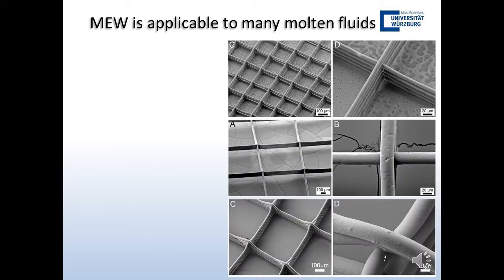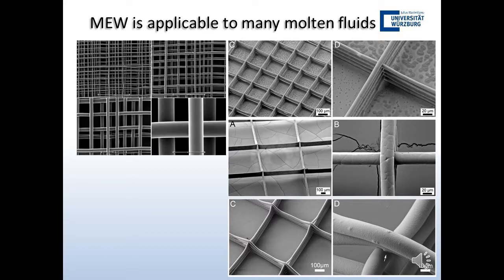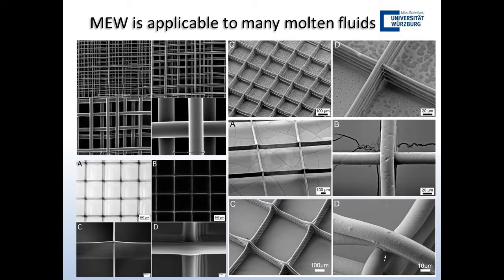And we find that MEW is applicable to many fluids, so polypropylene, polydioxanone, or PVDF. This is a photo cross-linkable polymer, and also thermoplastic elastomer. So we tried a range of different fluids, different polymers, and they all seem to work as long as there's not too much thermal degradation.